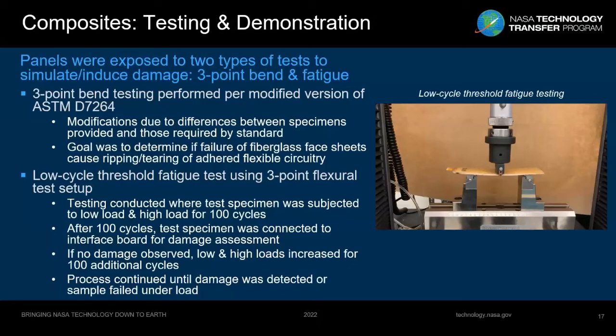And our overall goal of this testing was to determine if the failure of the fiberglass face sheets could cause ripping or tearing or damage to the adhered flexible circuitry inside the composite or laminate. And then the low cycle threshold fatigue testing used a similar setup to that of the ASTM D7264. The specimen was subjected to low load and high load for 100 cycles. After 100 cycles, we attached it to our interface board and assessed the damage. If no damage was observed, we repeated, increasing the loads until we actually got failure.